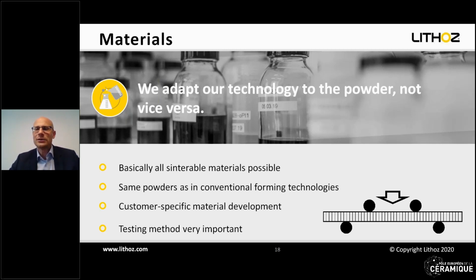But here, as you see it right now, you're testing along the layer. So you print the part like this, and you test it like this. This is very, very important, because not everybody is following this rule, and sometimes this could lead to a factor of 10 in strength values. So it's very important to know that, because additive manufacturing is a rather young field, and even some experts, or some already starters with additive manufacturing, have difficulties in